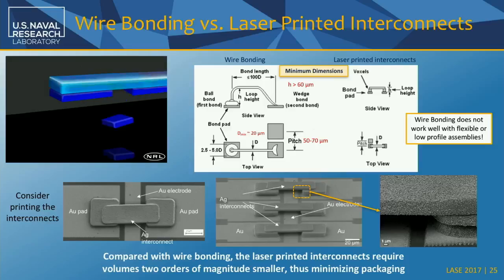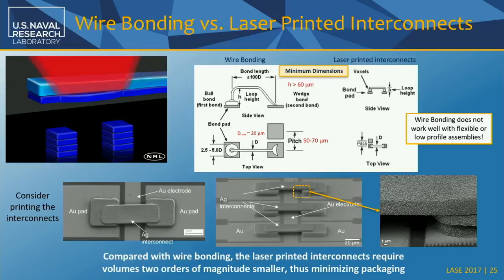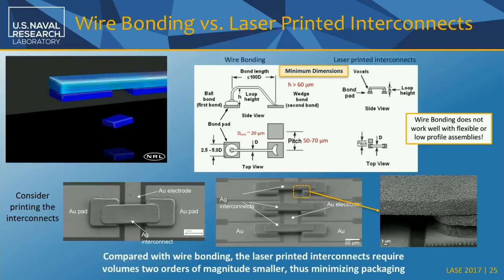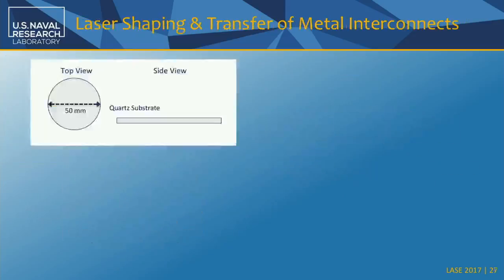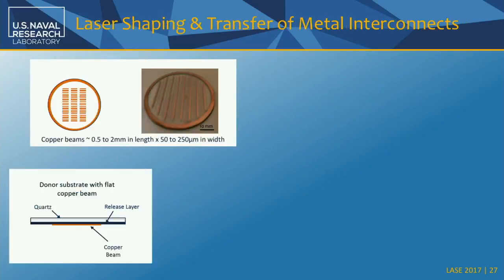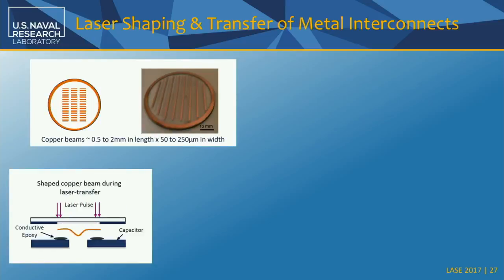So again, we can show interconnects as well, and this is to take advantage of the freestanding structures that we can make. But the last thing that I had here, and I'm going to move through this, was to show that we can also transfer metal foils when we need a high current application, if we need several amps in a circuit. And one of the issues that we have to worry about is we want to shape the foil so it can accommodate thermal mismatch strains on the part. And we can do that also with the laser. So we can shape first and we can transfer later.